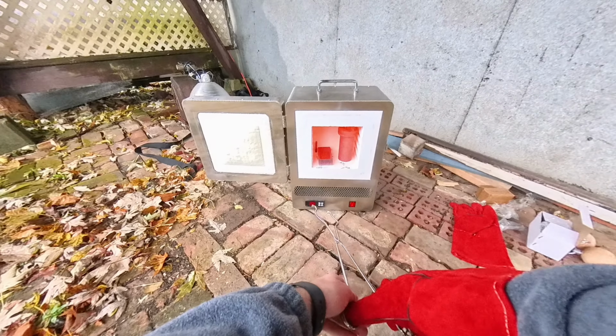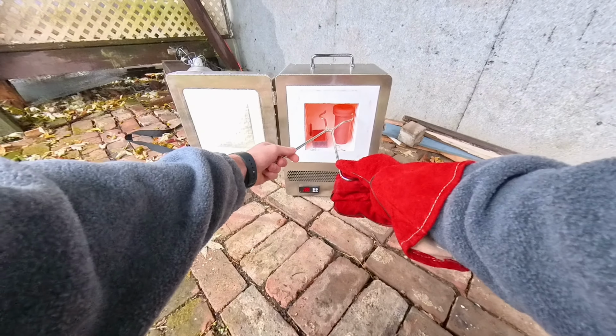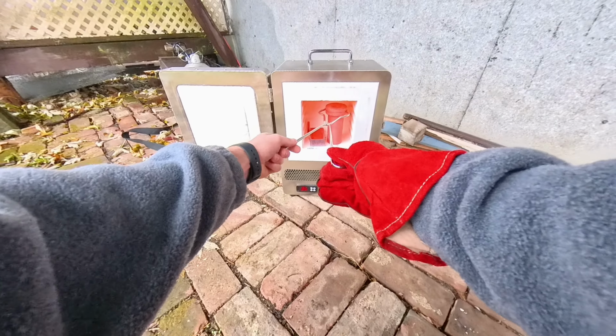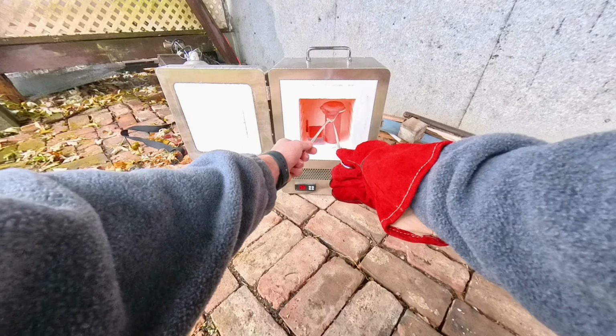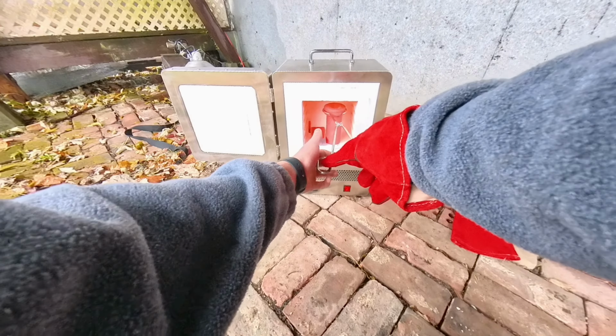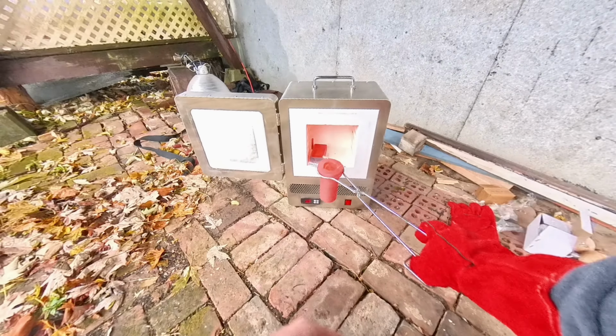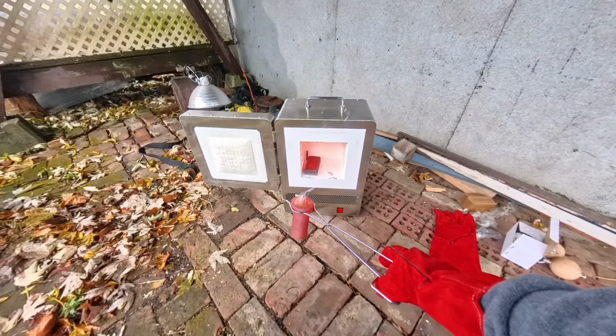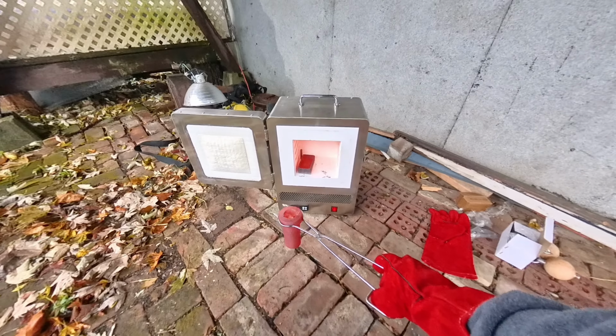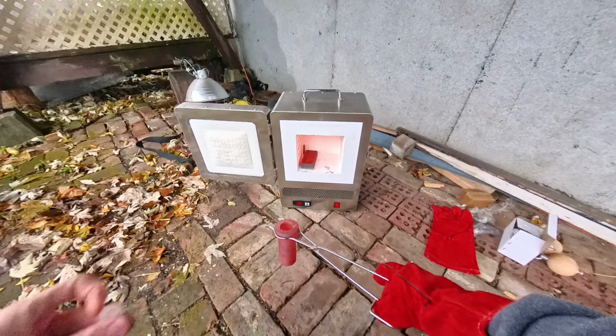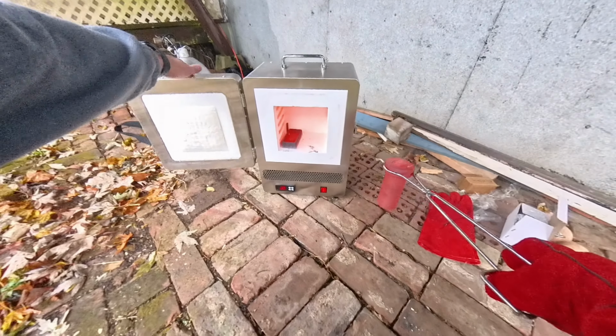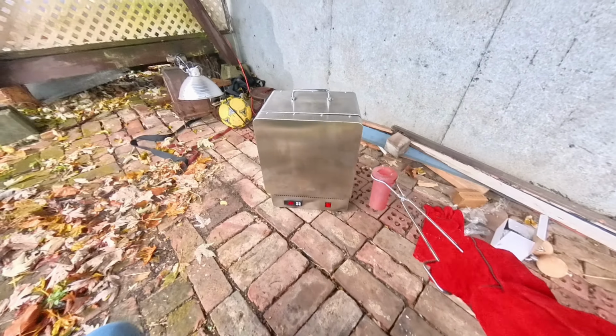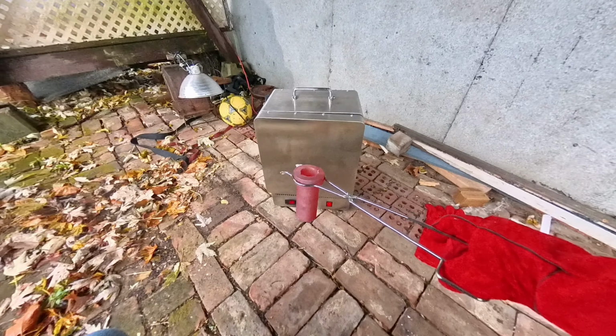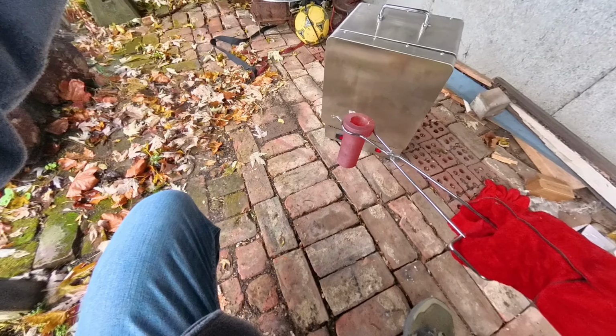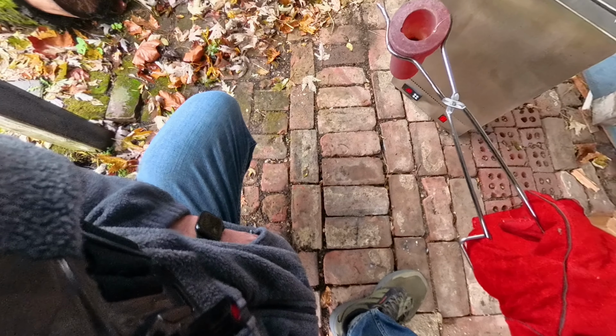Now, at this temperature, the zinc should not be boiling at all, but as you can tell by all that white smoke coming out of the top, evidently it is boiling and not insignificantly. I talked with Jason about this, and according to him, his furnace also ran hot, so this is an issue you're going to have to tackle in the future. Nonetheless, I still went on, and I added 80 old pennies to this mixture. This should get us a solution that's about 42% copper, so it should be fully liquid at 850 degrees Celsius.